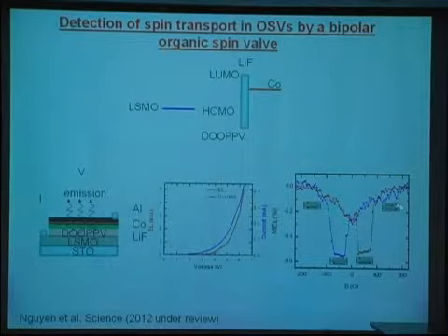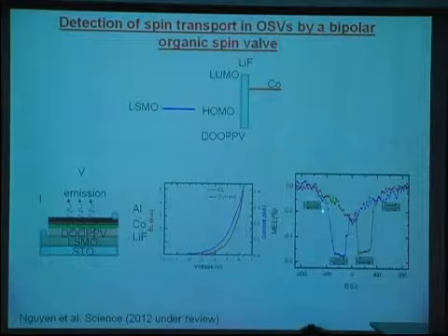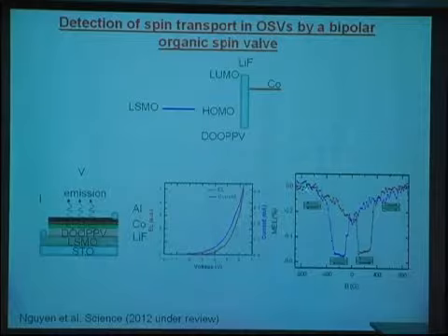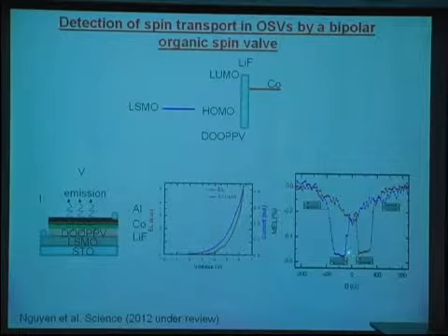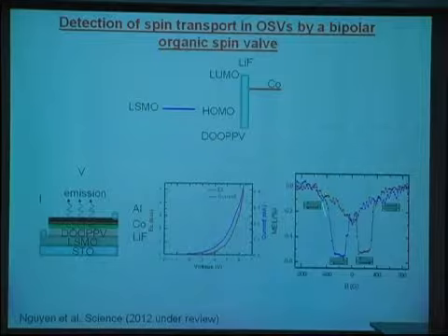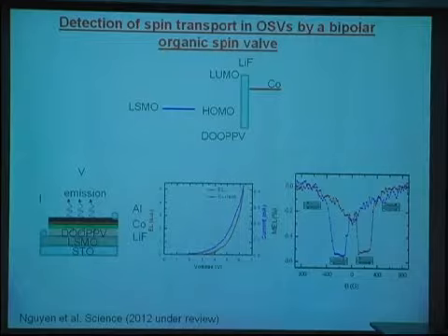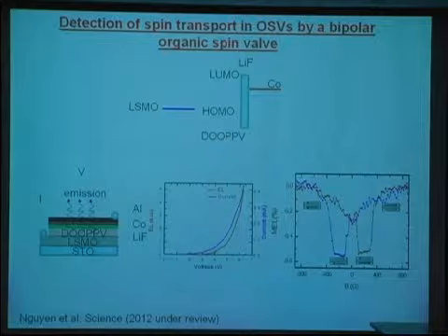Okay, so this is the result that we got. You can see here with the parallel configuration, we have the larger electroluminescence than the anti-parallel configuration. It's not exactly 50% quantum efficiency and 0% quantum efficiency here, because in reality we don't inject 100% spin polarization into